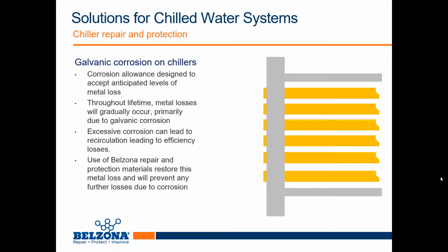We're going to move on to some tube sheets and the chillers as well. Chillers are a vital part of any heating or air conditioning system. You know, failure to quickly protect these units allows galvanic corrosion to take place, ultimately resulting in wastage and metal loss on the tube sheet around the coolant tubes. Left untreated, the loss of metal can cause leakage of the coolant and contamination of the chilled water.